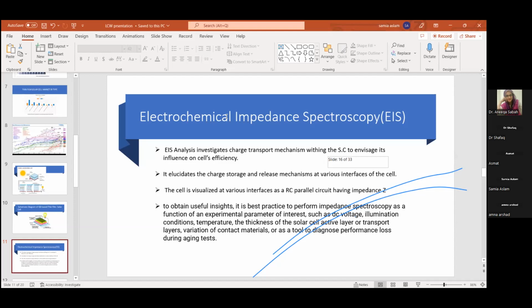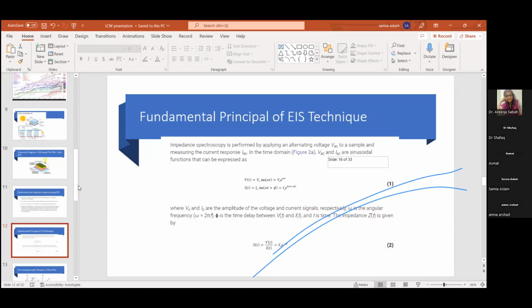So it means that EIS analysis is performed as a function of all these parameters. So it is the choice of the researcher how he or she is going to design the project to understand the electrochemical performance using this characterization technique. So what does it do? This characterization technique is simply that we apply an alternating voltage to the cell with a certain frequency or within a certain frequency range, which is represented here by the time domain. In fact, we are talking about the frequency, and then we see the current response of the solar cell.